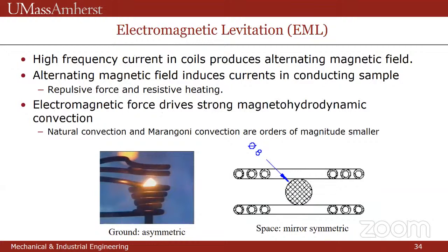And we're applying this for electromagnetic levitation. So we use a coil to induce currents in the field. The induced field opposes the applied field, so the sample tries to run away. And by controlling the shape and magnitude of the field, we can make the sample run away just enough that it floats here in space where you don't touch it. And so having done that, you have the opportunity to provide an environment that's free of heterogeneous nucleation, at least to a large extent, and to do other things to the drop.